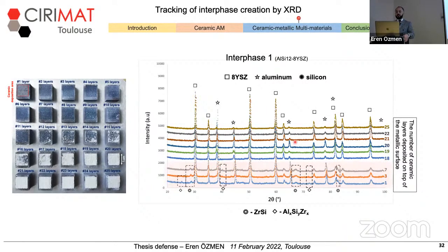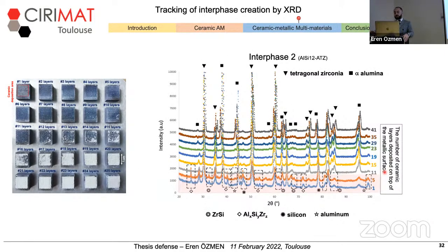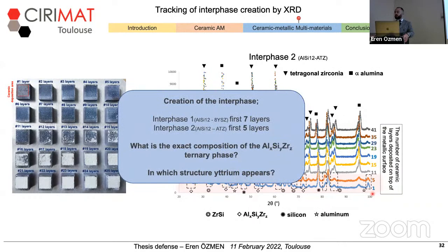So for the first interface, we can say that starting from the first layer up to the 7th layer, we observe the creation of the intermetallic phase and the ternary phase. And after the 7th layer, the composition goes exactly like the ceramic structure. After that, for the second interface, we also see the creation of this intermetallic phase and the ternary phase for the first 5 layers. And after this 5th layer, the composition goes as ATZ structure. So this part can be concluded as: for the first interface, it takes 7 layers for the interface to appear, and for interface 2, it's the first 5 layers.